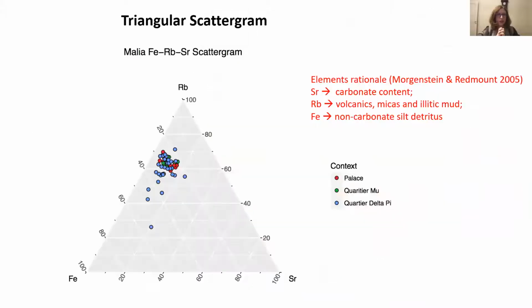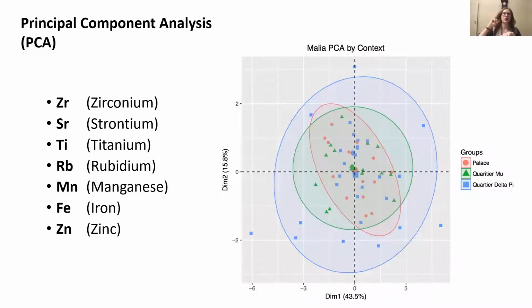If we go to the next slide, I just wanted to widen a bit my explanation on this. In this case, you see the principal component analysis that is being performed on all the samples that I collected in Malia. And you can see the different ellipses indicating the Palace, Quartier Mu and Quartier Delta. The majority of the samples were actually coming from the building Delta B, but we also had samples from Delta Alpha and Delta Beta. They show the same pattern of continuity and consistency of raw sources, indicating that this chronic consistency is not just present in the Palace, but in all of the settlements in Malia.